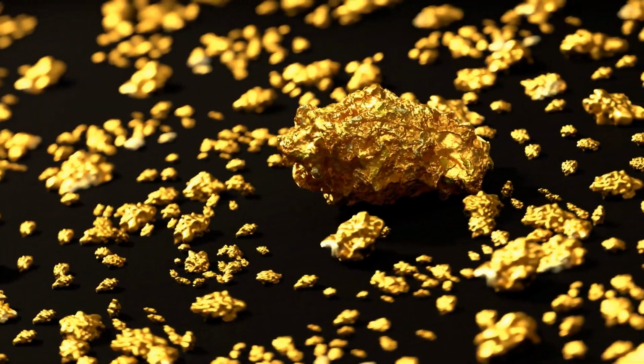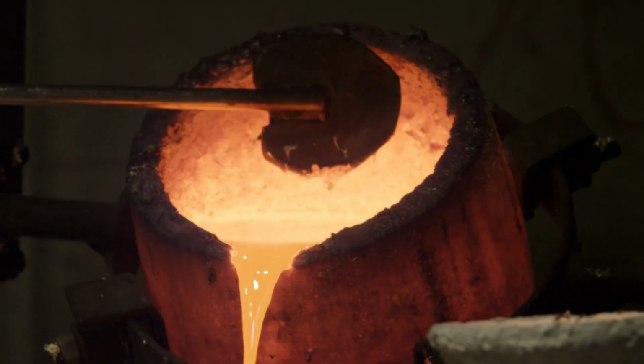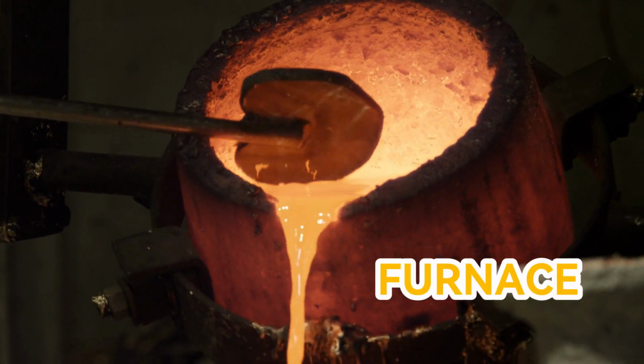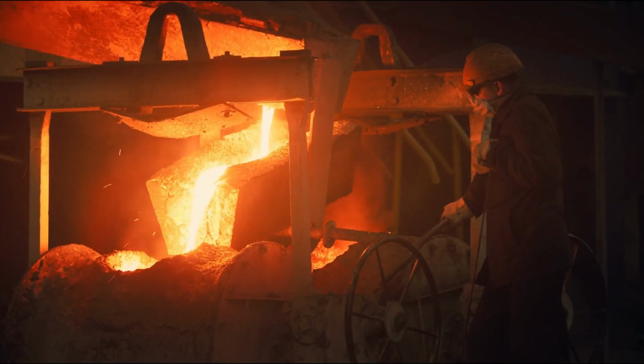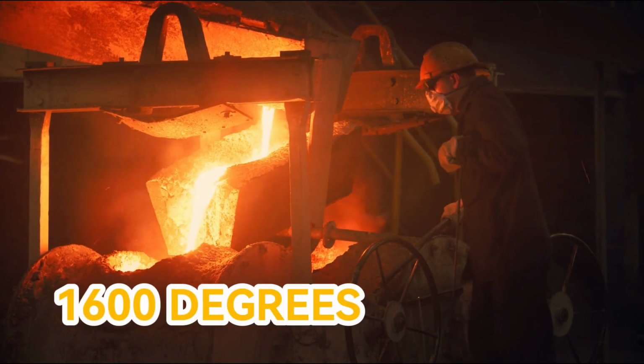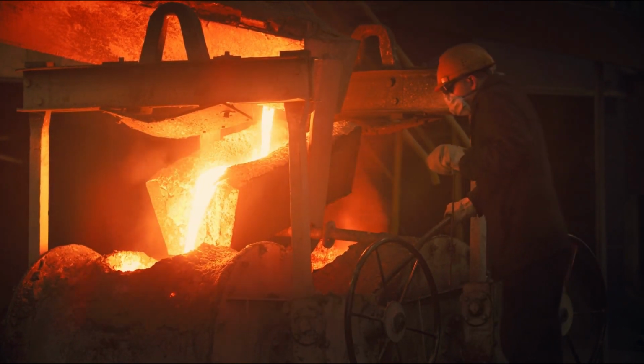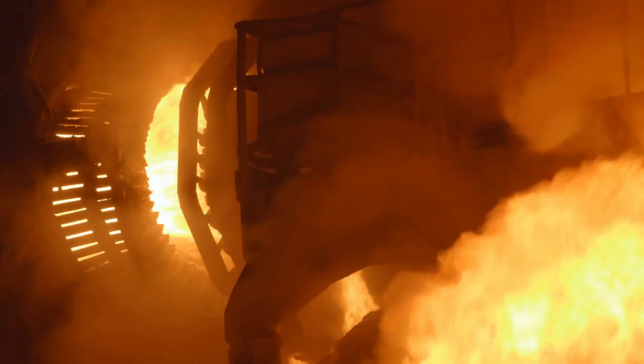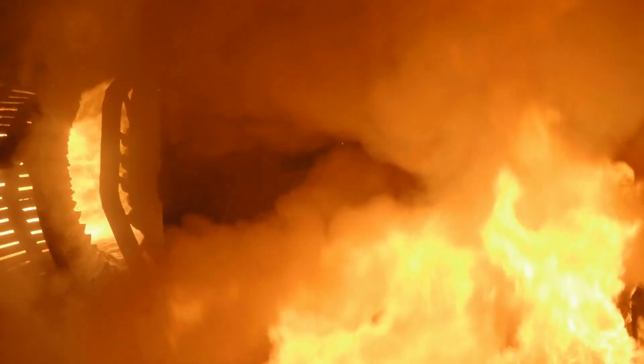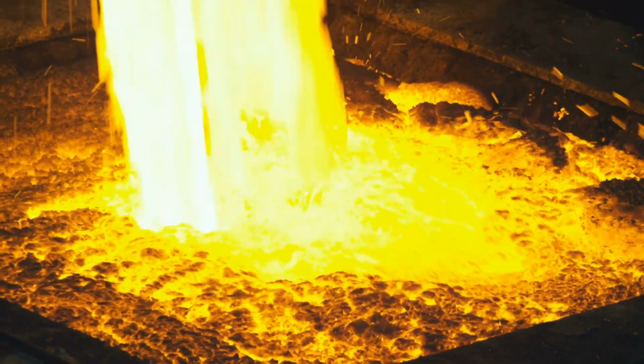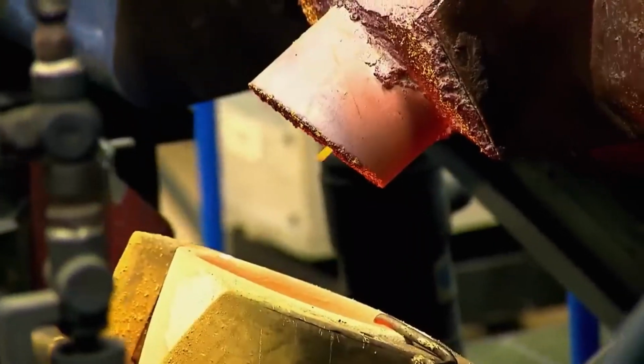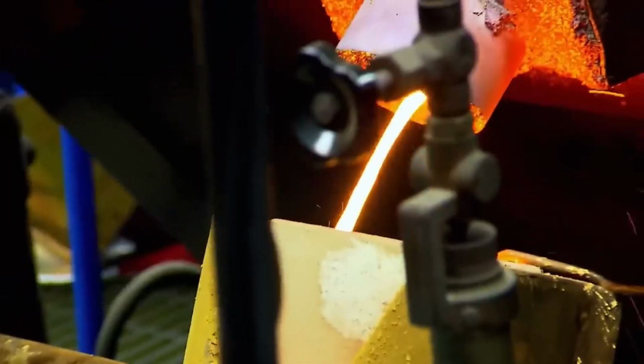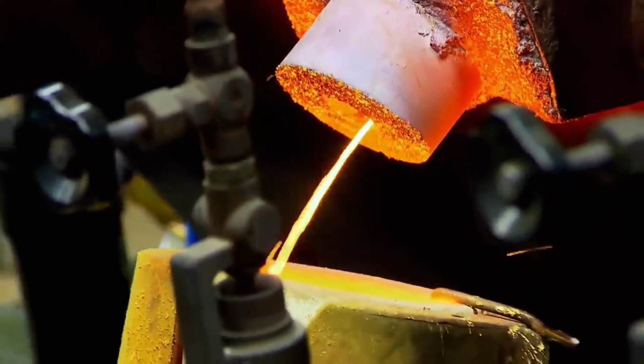gold from other elements. The gold concentrate and flux mixture are introduced into a specialized high-temperature chamber called a furnace. Inside the furnace, the mixture is exposed to temperatures as high as 1,600 degrees Celsius, causing it to melt. The furnace is rotated to ensure even heating throughout the mixture. The extreme heat effectively separates the gold from other elements present in the concentrate, such as base materials and impurities. As the material melts, it separates into distinct layers based on their densities, with the gold sinking to the bottom due to its higher density.